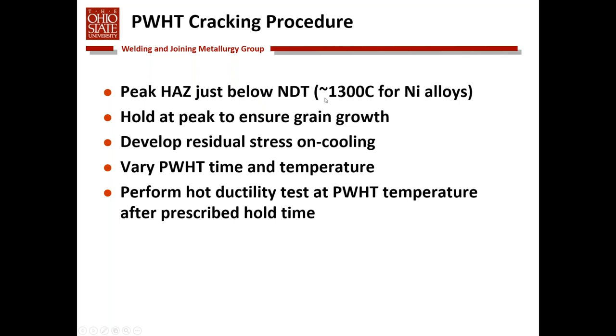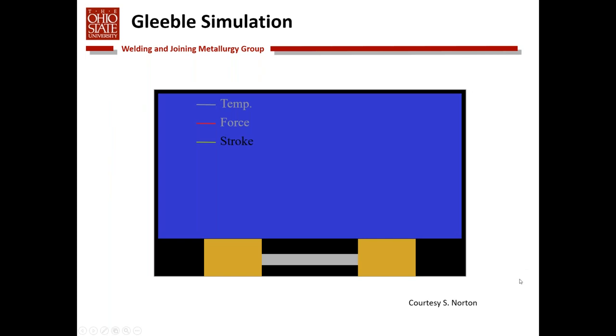So the procedure that we've developed is basically to take a sample and heat it to a temperature below the nil ductility temperature, so in the solid state, approximately 1300 degrees C for nickel alloys. We hold it at that temperature for a few seconds to get some grain growth, and then we develop a residual stress by straining the material as we cool it. Then we perform a post-weld heat treatment at different times and temperatures, and then we pull that sample to failure at the post-weld heat treatment temperature to determine the ductility. So this schematically shows what's going on.